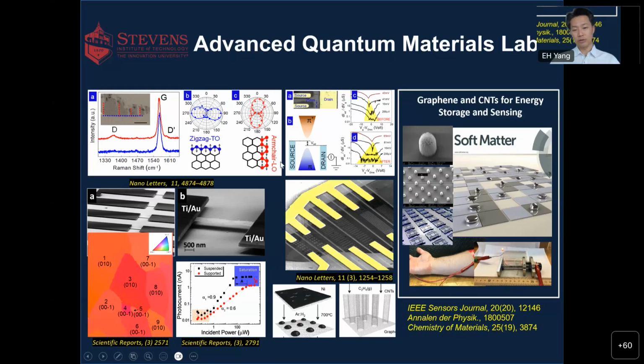We also worked on the growth mechanism of graphene related to the substrate, which is copper in this case. We also had these projects on graphene photodetectors. We created this graphene and levitated this graphene microribbon here. Then we elucidated the mechanisms, and we learned that the photoelectric effect dominates the dynamics in getting the photocurrent out of these structures.